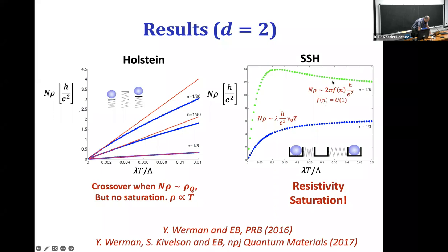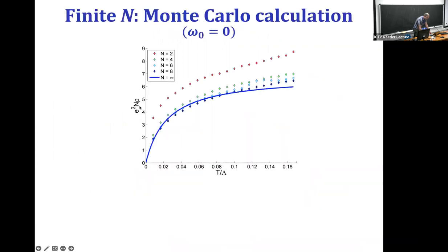And in this particular case, we can test how bad the approximation of setting n to infinity is. In this temperature regime, where the temperature is much bigger than the phonon frequency, we can treat the phonons as essentially static. We can solve the problem numerically and calculate the resistivity using Monte Carlo for a finite n. So here's n equals 2, 4, 6, 8, and here's infinity. At least qualitatively, the large n limit actually captures the behavior of this model, even for n as small as 2 or 4.